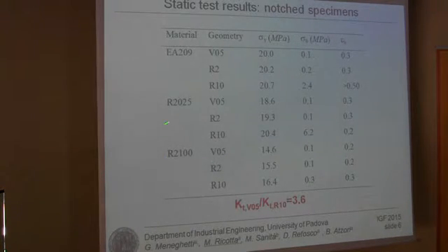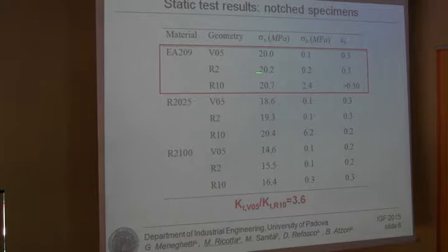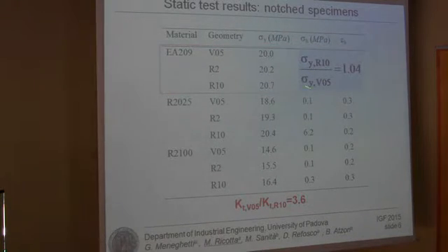This table summarizes the results obtained in the case of notched specimens. Keeping in mind that the theoretical stress concentration factor increases by a factor of 3.6 when reducing the notch radius from 10 mm to 0.5 mm, we can see that in the case of the first material, the yield strength is constant from an engineering point of view. If we define this simple ratio, the yield strength evaluated in the case of 10 mm with respect to that evaluated in the case of 0.5 mm, this ratio is practically 1.